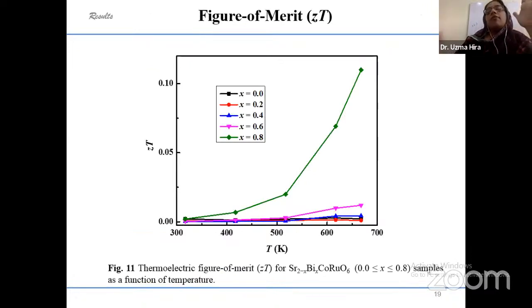So at the end, we have all these three properties: Seebeck coefficient, electrical resistivity, and thermal conductivity, and we have calculated the ZT value by using these three parameters. You can see our pure compound has very low ZT value, but with the highest dopant content, we have obtained the maximum ZT value, which is greater than 0.10.